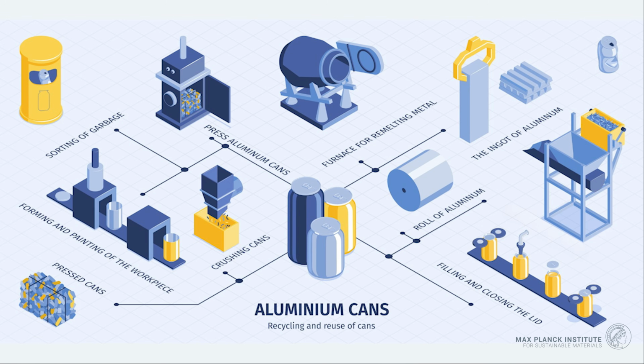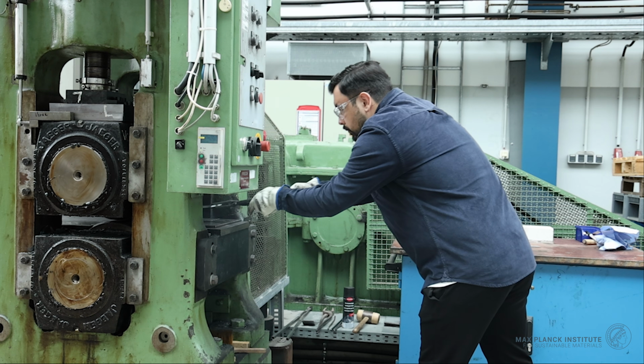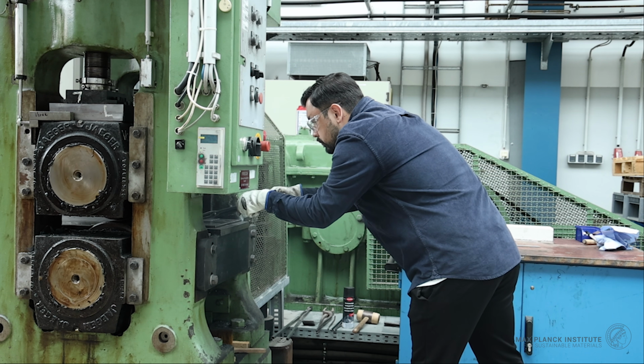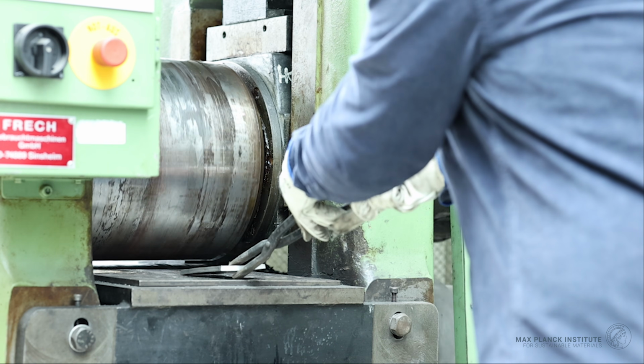So, for beverage cans, the aluminum alloys have to be strong, light, formable, easy to manufacture in large quantities, and nowadays, increasingly circular. Imagine that you are in industry and the beverage cans that you recycle in your supermarkets come back to the melt shop. In industry, we melt those beverage cans, we cast big ingots, and then those ingots are heat treated. After heat treatment, they are hot rolled, cold rolled, and then they are shipped to the can maker.